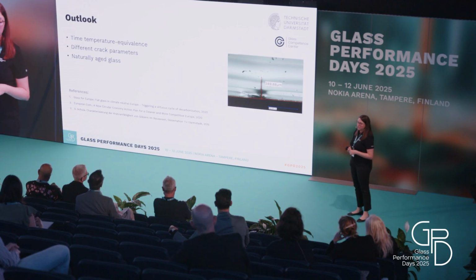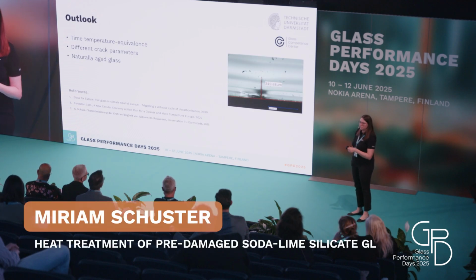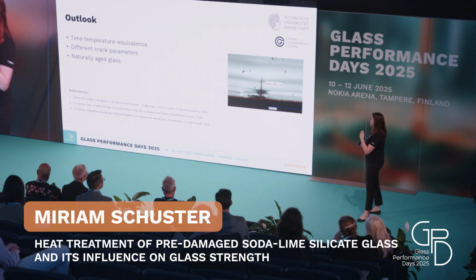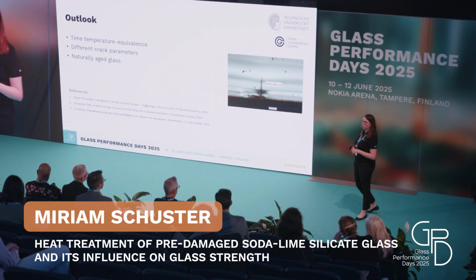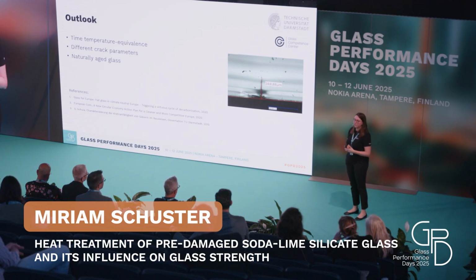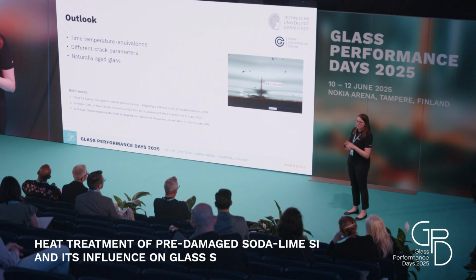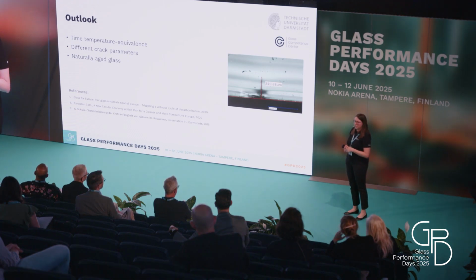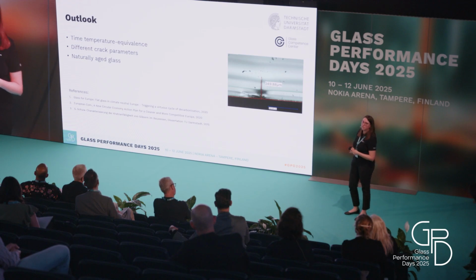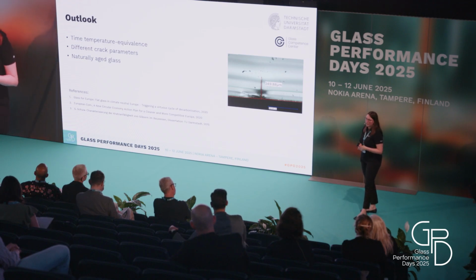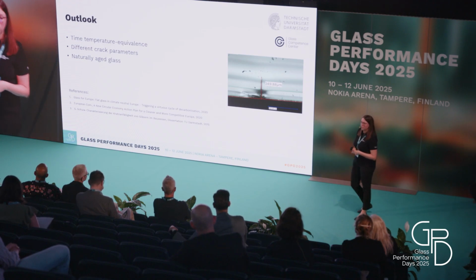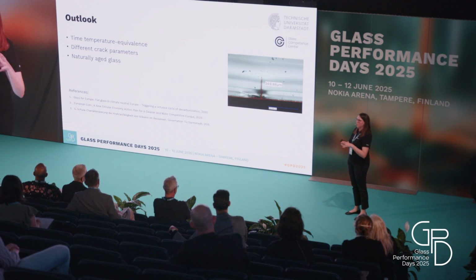Then we already started a different series with another crack geometry, because the crack that we investigated here was quite small with this 58 micrometers depth. And in the second series, we are investigating a crack that has a depth around 250 micrometers, so much larger. And then we also want to look at naturally aged glass, which might have different crack geometries on its surface. And finally, it's also important to scale this up.